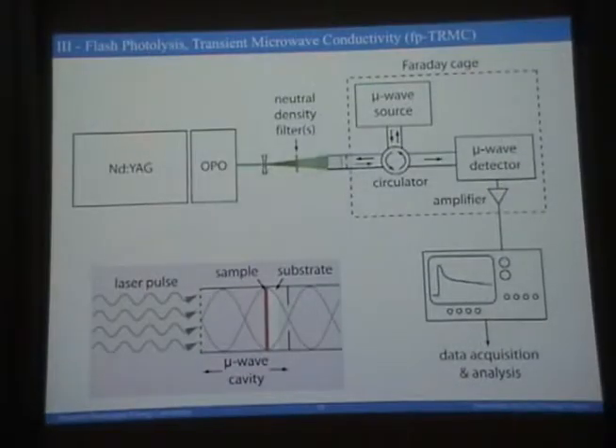So here's my experiment. I won't show you photographs of it because it's very, very old equipment and doesn't look very impressive. But the nice thing about this approach is the following. First thing is that relative to terahertz spectroscopy, it's much, much slower. It's only a nanosecond technique, not a picosecond technique. But I've already shown you that if you do a fast experiment, you get misled because you don't see the carriers you'd expect. This is slow. It's timed to get those carriers.